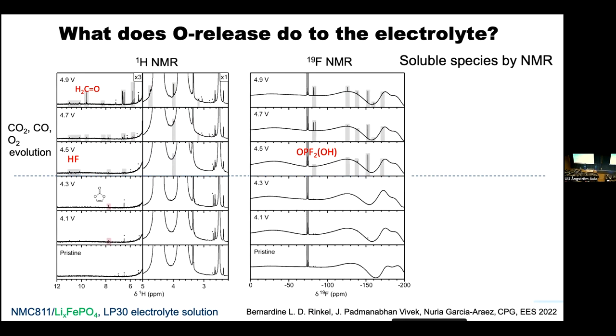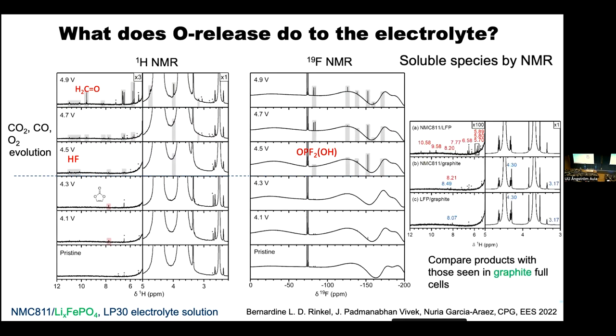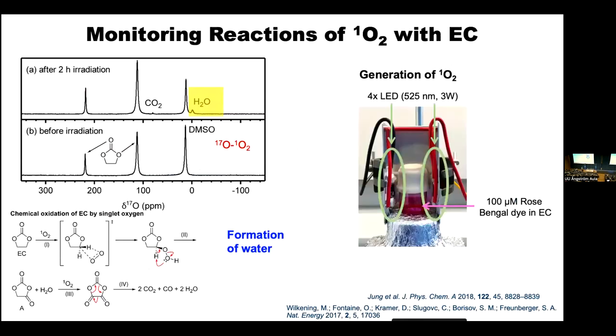So can we understand those mechanisms? What we did was to actually create singlet oxygen using rose Bengal dye. We took singlet oxygen created from O17. We could then follow the reaction products by using oxygen NMR, and we could show quite clearly that you formed water, and this was consistent with this mechanism, based on others, including Hubert Gasteiger's work, to generate the water in this reaction.